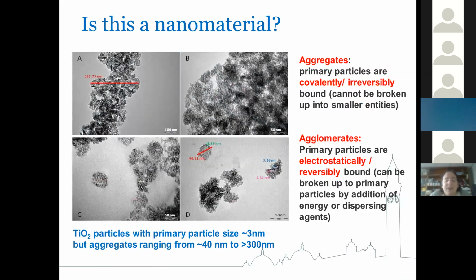Also, I've alluded to this already, but some nanomaterials will have a primary particle size, but in reality you will rarely get the individual particles. You might get clusters of the particles, and these clusters might be different sizes as well. So this is a case of some industrial titanium dioxide, TiO2. The primary particle size is 3 nanometers, so that's this tiny piece here. But no matter how much energy we put into the system, we've never been able to get back to 3 nanometer particles.